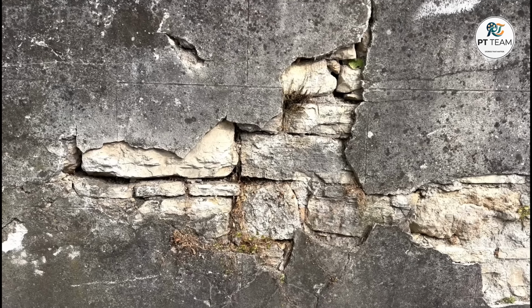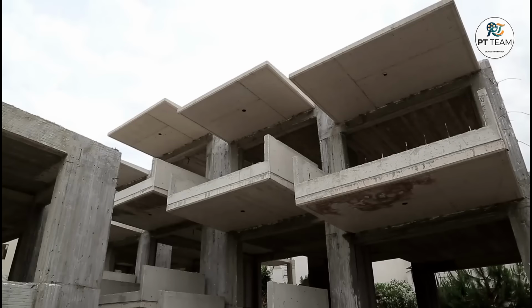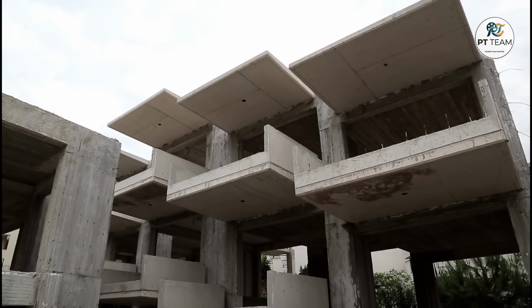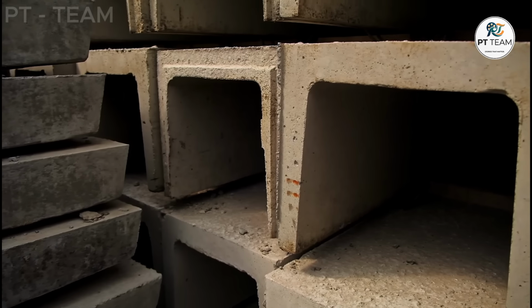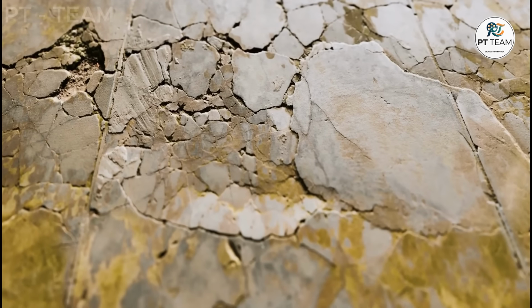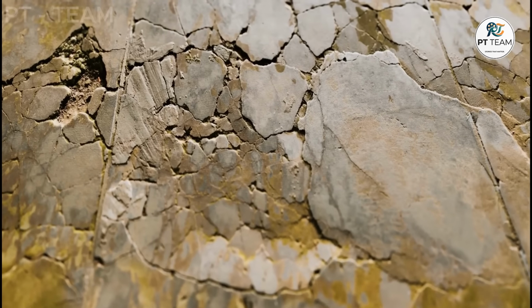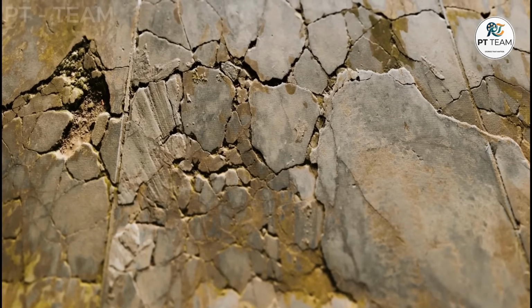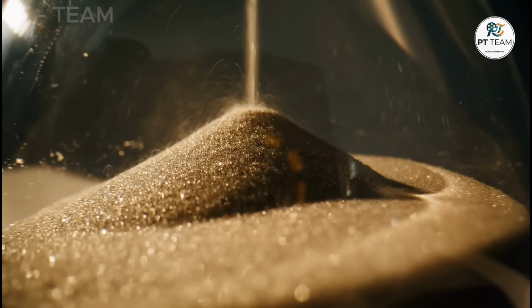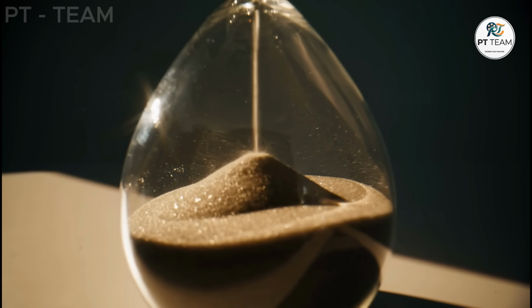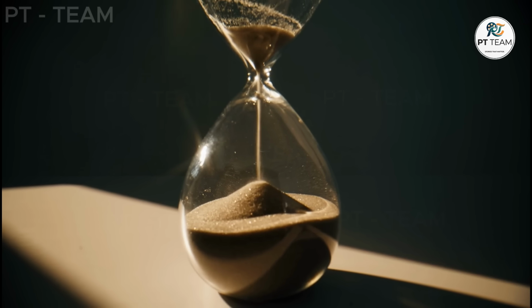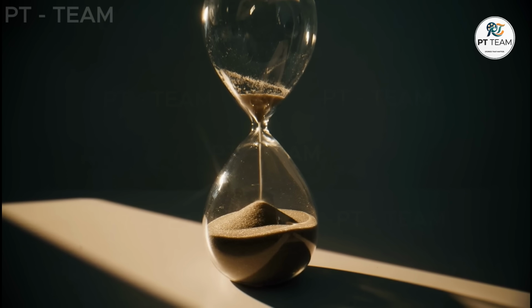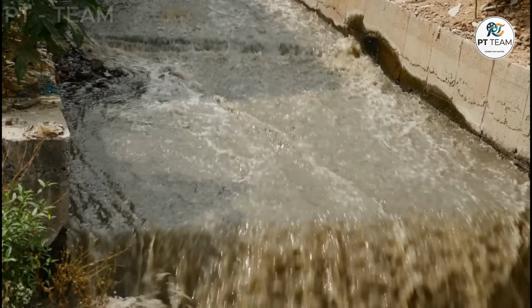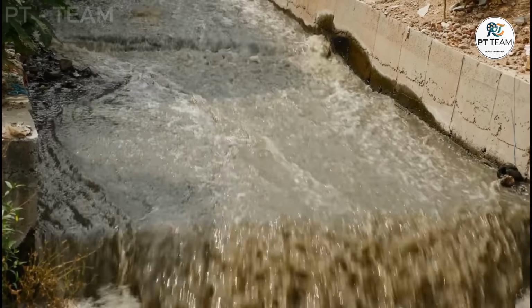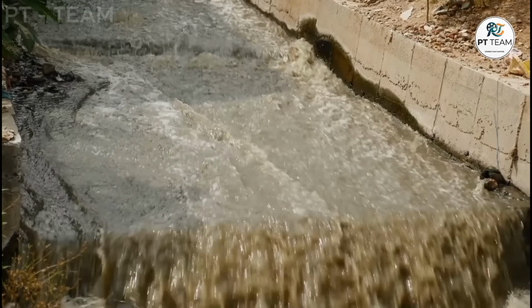From the moment that first visible crack appears, the building has inadvertently opened the door for a secondary wave of attacks. We have now entered a self-accelerating feedback loop. Before the crack appeared, the chloride ions had to slowly navigate the microscopic maze of pores to reach the steel. It was a difficult, time-consuming journey. But the new crack creates a massive, unobstructed superhighway leading straight into the heart of the structure. Water, oxygen, and fresh salt can now pour directly into the core without any resistance.